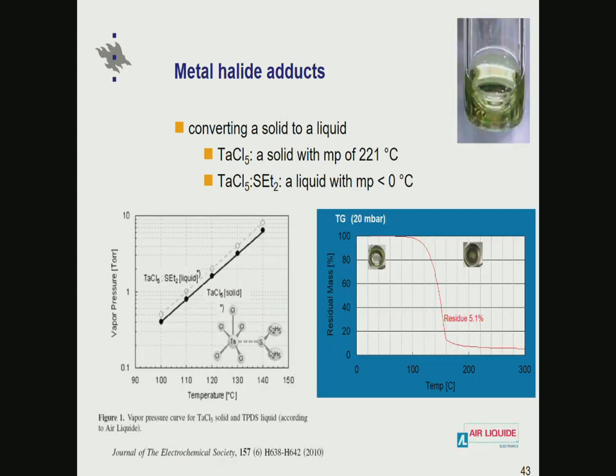Earlier, Air Liquide was dealing with the problem of tantalum chloride being a solid. So they made this kind of a thioether adduct of tantalum chloride. They converted that into a liquid. It had very little effect on the vapor pressure, but it changed the phase to the more desired liquid.